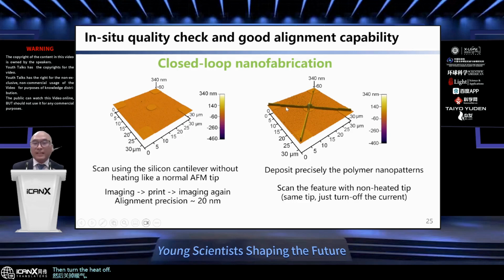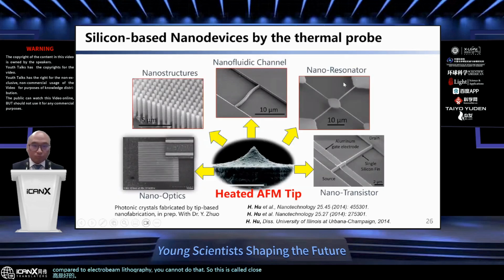Then we can deposit the nanoscale polymer patterns. And after patterning, we can immediately turn off the current. The probe becomes a normal probe again. We can use the same probe at the same place to do in situ scanning and get the image. So in this way, we can immediately check whether this deposition is good or not. Compared to electron beam lithography, you cannot do that. So this is called closed loop nanofabrication.